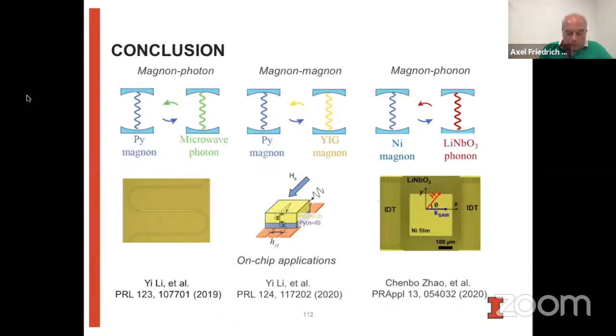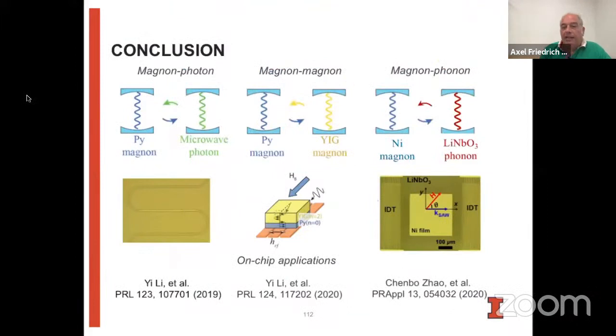Okay, so first of all, growing the permalloy on top of the niobium nitride is very simple. You can easily do that. If you want to grow YIG on top of the niobium nitride and do it well, that's really hard to do. Then the other possibility is you grow yttrium iron garnet on GGG and then put all your superconductor on top. But it turns out that's not good either, because GGG is a frustrated magnet that has all kinds of magnetic stuff going on at low temperatures. And it turns out that if you look at YIG on GGG at low temperatures, it doesn't have low damping anymore because of the coupling to the GGG substrate. So YIG at low temperatures is a real headache to do right.